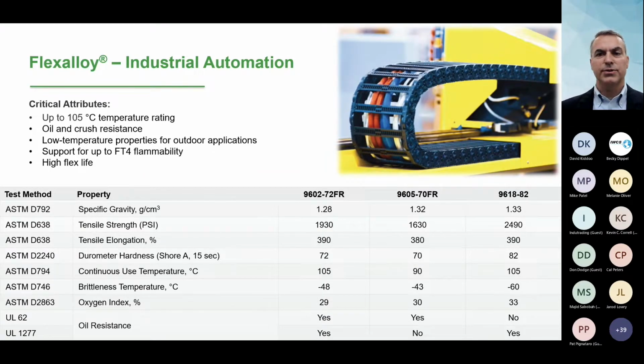For rapidly emerging industrial automation applications, we suggest 3 jacket compounds for consideration. The 960272FR, you've already seen as a workhorse compound. 960570FR is even more flame retardant with a typical LOI of 30% for cases where the cable core material may be somewhat more flammable, right? It's always the whole cable design. You need to take into consideration how all the different components balance each other. Flexalloy 9618 offers the highest flame retardancy at 33% LOI, along with a brittleness temperature measured of at least minus 60 C for cables that need to pass very low cold temperature impact tests. So a good range of products for different applications.